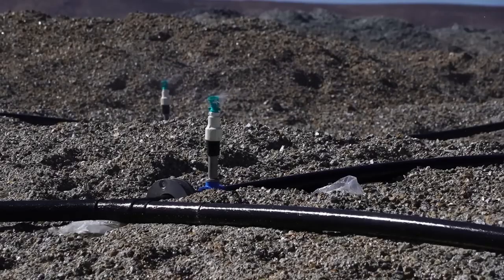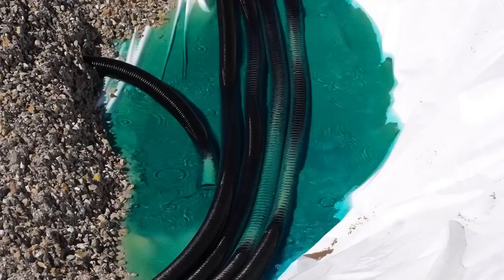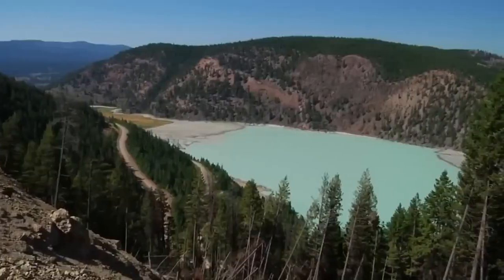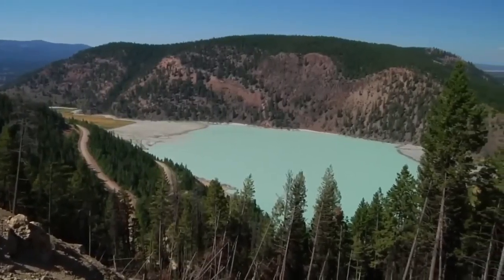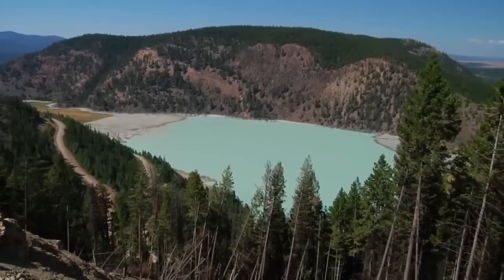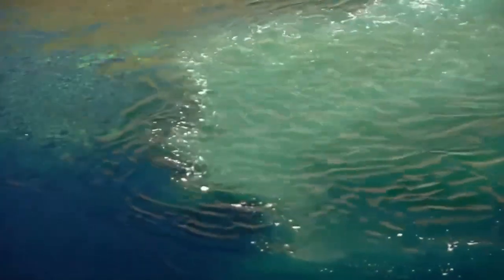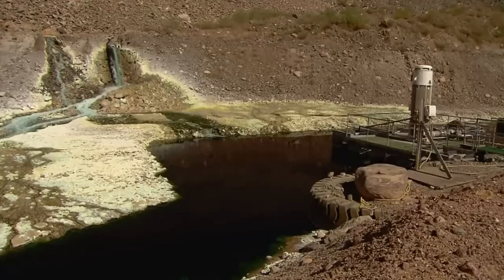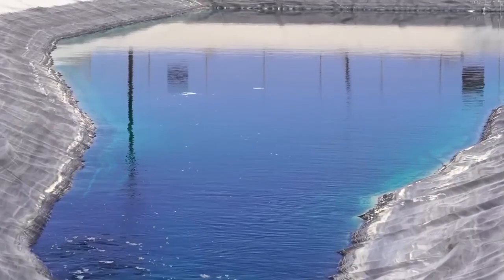Over weeks, this acid slowly seeps through the rock, dissolving the copper. The solution, now loaded with copper ions, is collected in ponds and directed to the processing plant through a special channel. The copper solution is combined with an organic reagent and floats to the surface. Then an acidic solution is added to increase the copper concentration and make it electrically conductive.